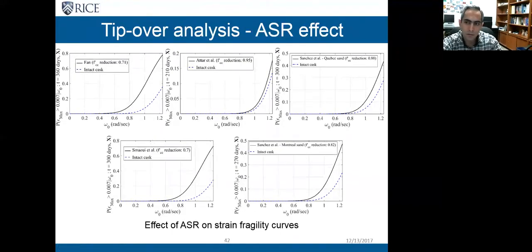Another application of the meta model that I showed is studying the aging effects on the cask. As I mentioned, the casks have to be used for long periods of time, and aging is a threat. In these figures, I am studying the ASR effect on the casks. ASR is a phenomenon in which usually the mechanical properties of the cask concrete are affected, and usually the compressive strength, tensile strength, and modulus of elasticity reduce. So if we can combine studies on ASR effects on concrete with the meta model that I just showed, we can update our fragility. And these are the results from five different studies on ASR.